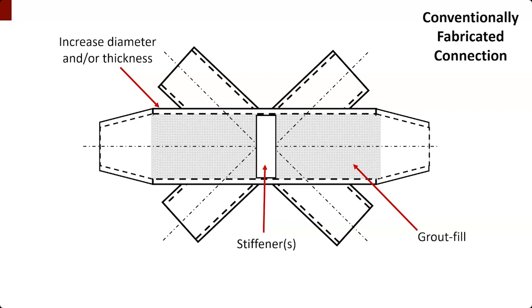But then once the D over T ratio, or the wall thickness to the diameter of the connection, becomes flimsier and softer, there is need for these internal stiffeners. It's difficult to fabricate, to stuff a plate inside of a tube and then weld it, get someone in there and hopefully not leave them there after the connection is fabricated, or grout filling, or all sorts of things. But this is basically exemplifying that it was increasing the complexity of fabrication as well as overall increasing tonnage at each one of these connections, which makes the structure more costly.